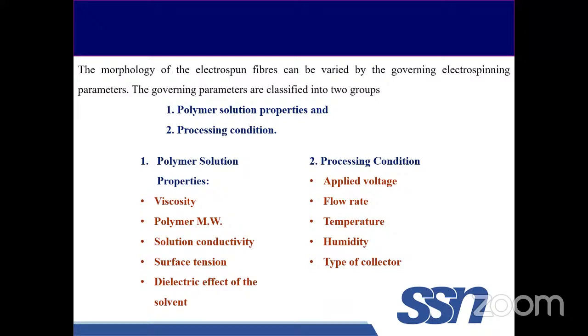So we can play with the viscosity of the solution. We can play with the molecular weight of the polymer that we are going to utilize, as well as the solution conductivity, surface tension, and the dielectric effect of the solvent that we are utilizing to dissolve the polymer, right? So by playing with these solution parameters, we can control the size of the fibers that we need to prepare based on our application.